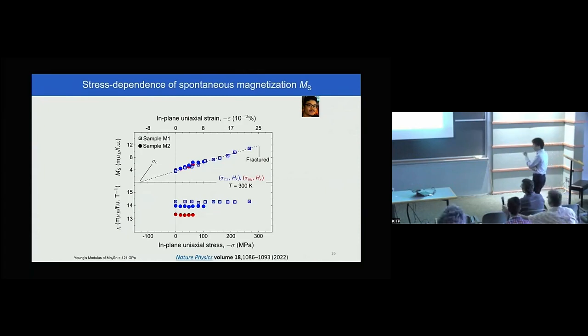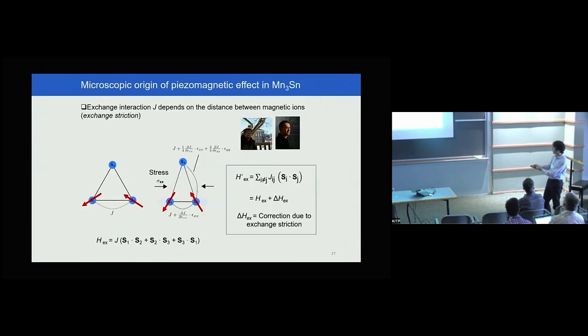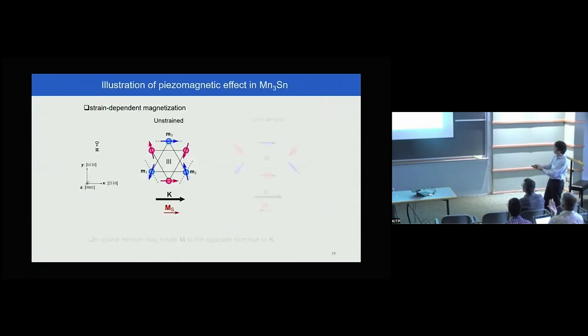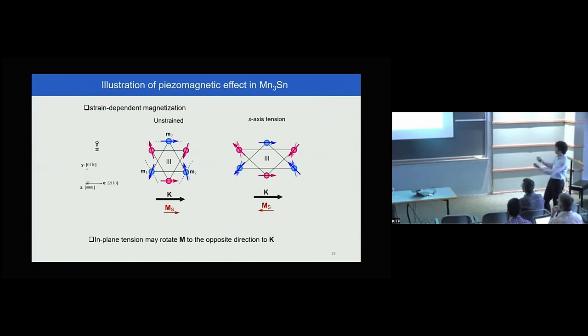Okay, so here what is important is that these spins are really frustrated. In this particular material, it's the frustration, and a tiny strain was enough to tip the balance of the cancellation of sublattice moments, right? So by just changing a small bit of strain, one can actually flip the magnetization direction, because you can change the canting direction a little bit. That was actually enough.